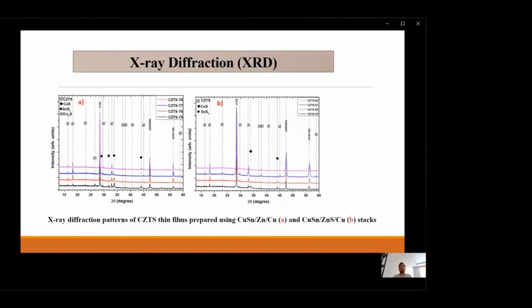The X-ray diffraction, we take it to examine the crystal structure of the films. As you can see, for the A-type and B-type samples, regardless of the sulfurization temperature or stacking orders, all of the samples are dominated by diffraction planes of the kesterite CZTS phase. As you can see, here's the 112 plane, 220 plane, and 212 plane. For both samples, they dominate all the patterns.